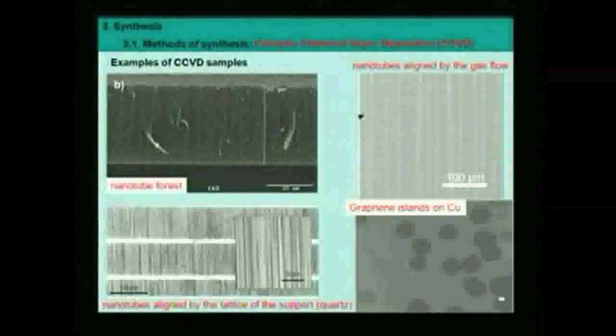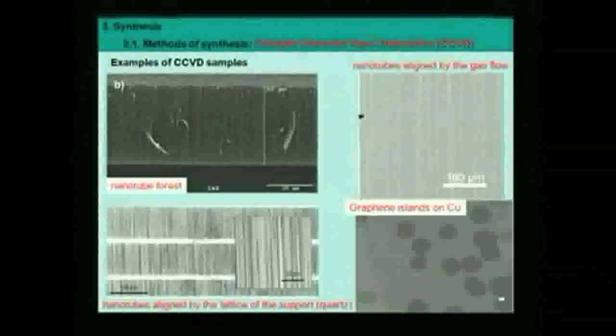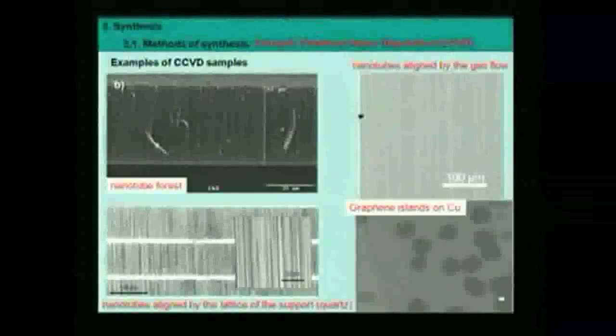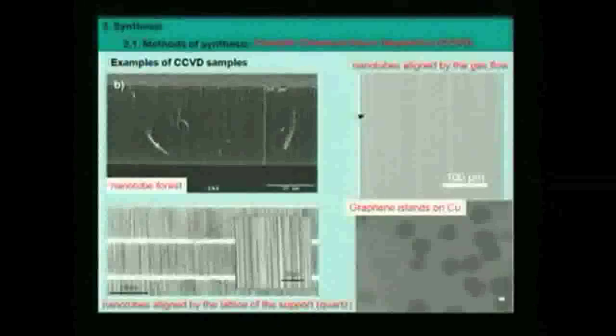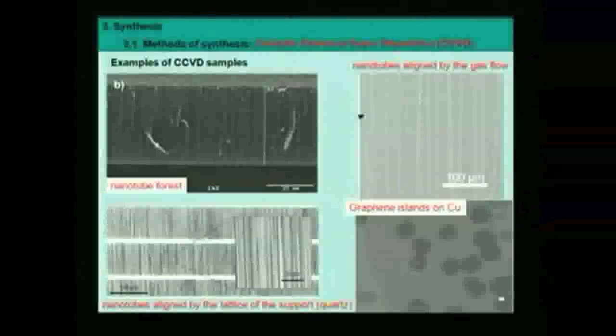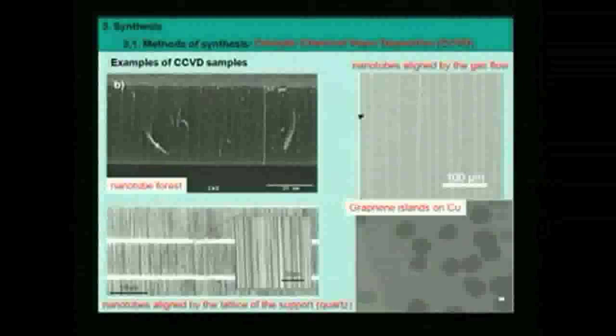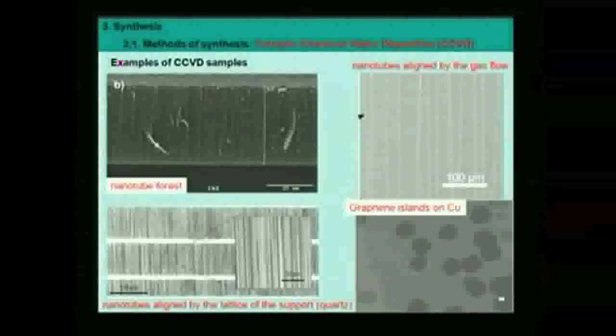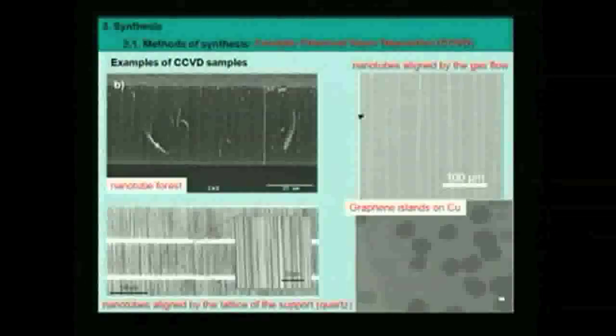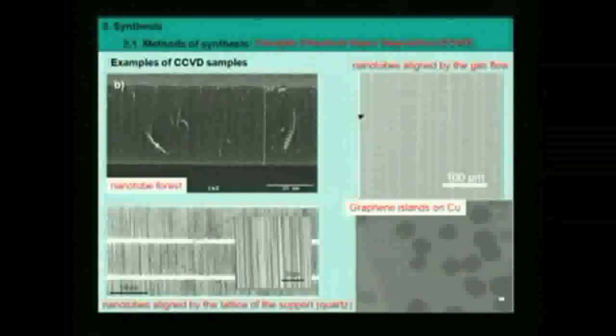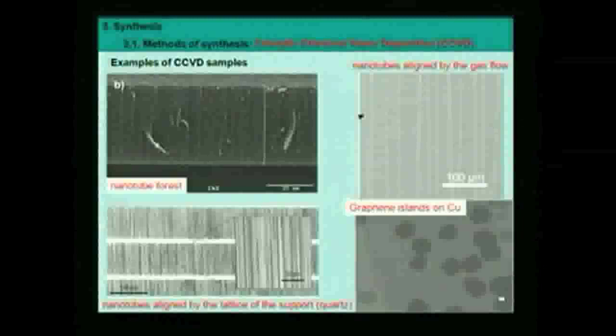No, not between nanotubes, between nanotubes and the substrate. In this case, this is different. Here, to get this alignment perpendicular to the substrate, you need a very high density of nanotubes. Why? Because you need steric interactions between them. You need them to repulse each other in order to have no other choice than to grow perpendicular to the surface because of the steric interaction between the tubes. Okay, so in this case, this is a tube-tube interaction that allows the growth of tubes perpendicular to the surface. Okay?